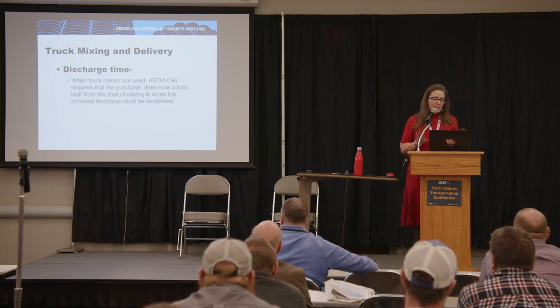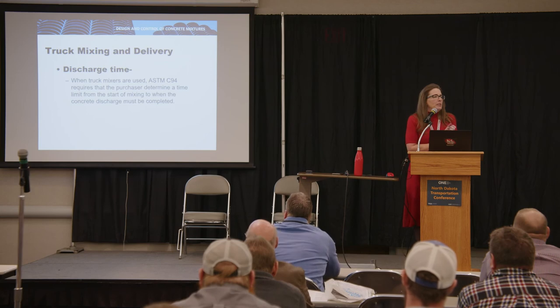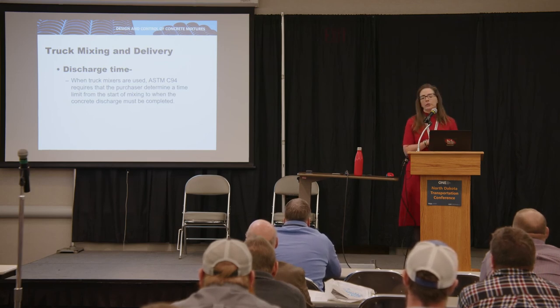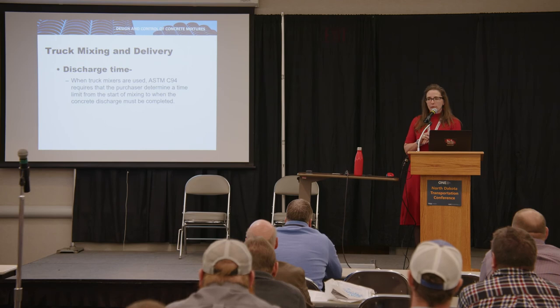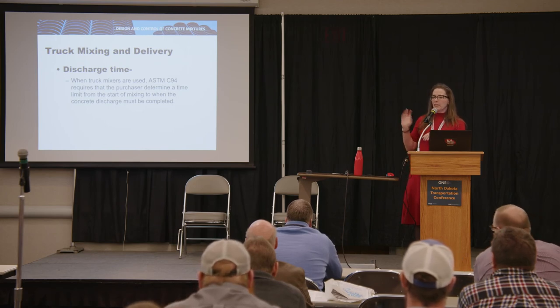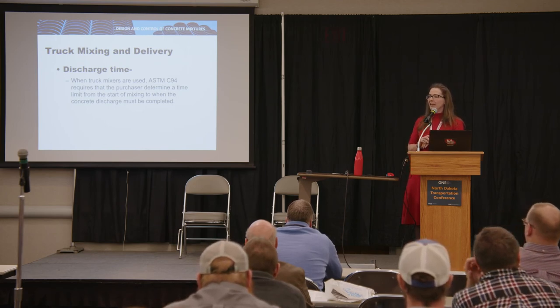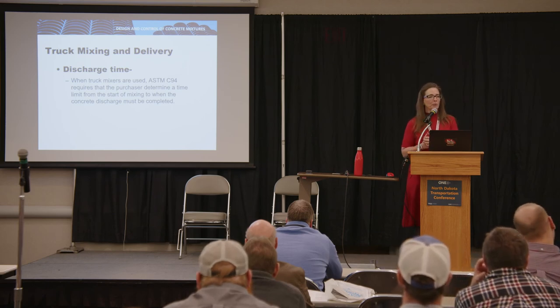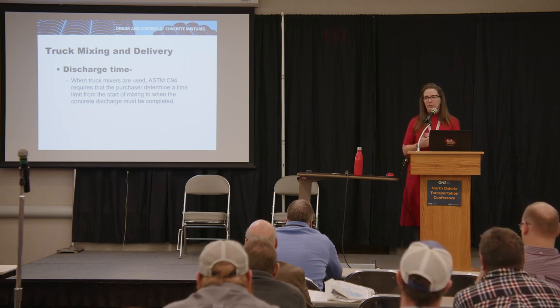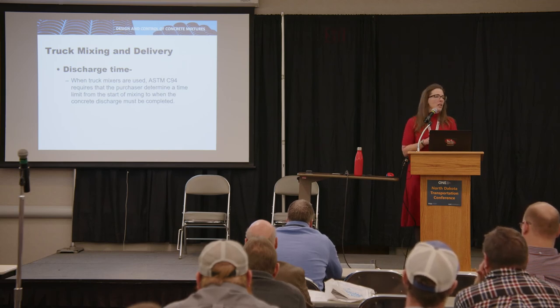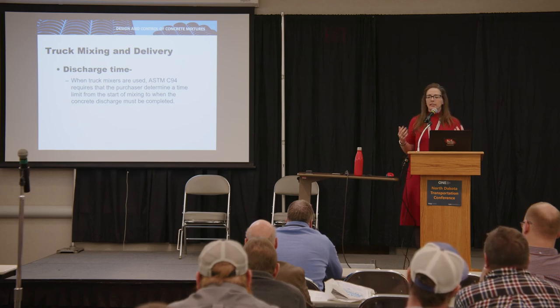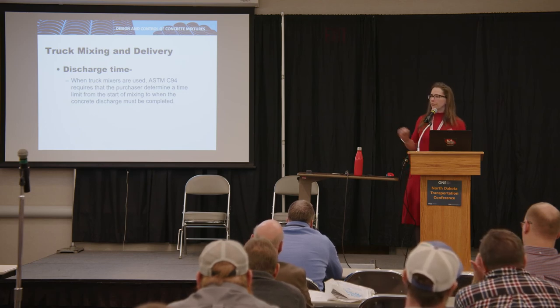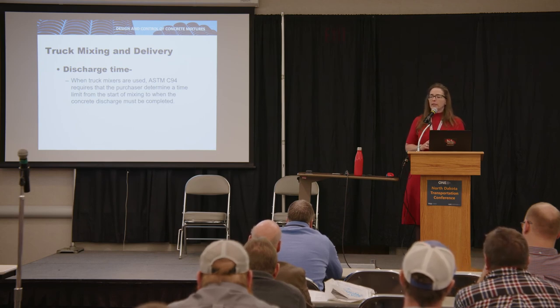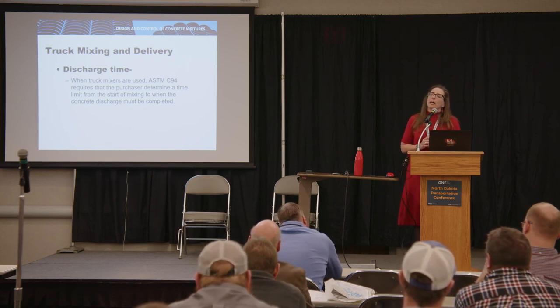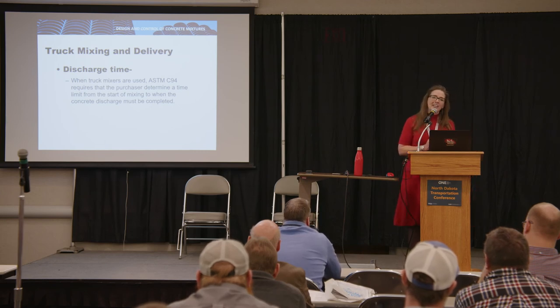So they changed it. They felt that 90 minutes was not tied to concrete in 2022. What it was tied to is concrete in the 1950s that was between 60 and 80 degrees Fahrenheit on a given day at a water cement ratio of approximately 0.5. Is that concrete in 2022? Not necessarily. There's a lot of concrete that sets up in a half an hour, 40 minutes if it's paved. There's a lot of concrete that takes 3 hours to set, initial set I'm talking, not final set. And I agree that 90 minutes isn't an answer, but it covers us. It's a CYA spec with the 90.